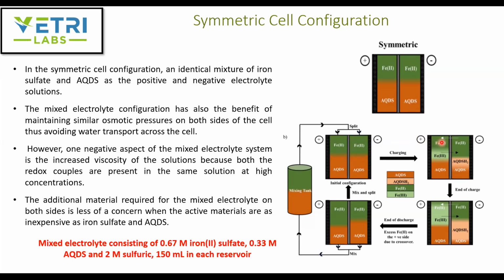And when you charge, you have Fe2+ getting converted to Fe3+. And we can make sure that at the positive electrode during charging, only iron 2+ gets oxidized to iron 3+, because AQDS present on this side cannot be oxidized further at the potential of that positive electrode. At the same time, on the negative electrode during charging, only AQDS is reduced to AQDS H2, and iron 2 cannot be reduced at the potential where you are reducing AQDS. During the discharge, the iron 3 is reduced to iron 2+ at the positive electrode, while the AQDS stays unaffected. And AQDS H2 at the negative electrode is oxidized to AQDS, while the iron 2 remains unchanged.